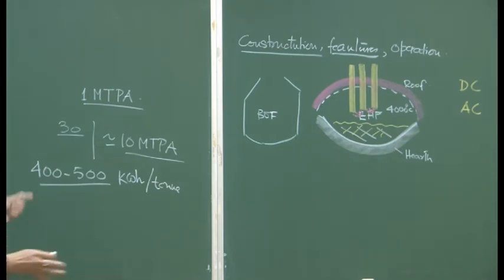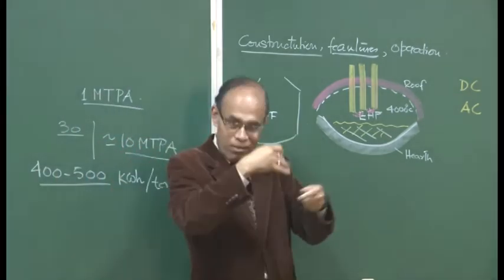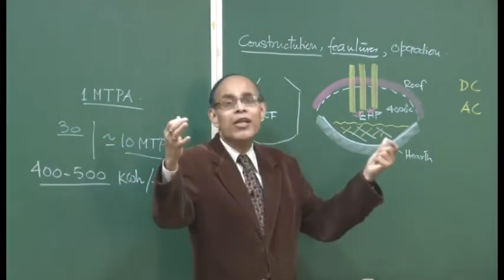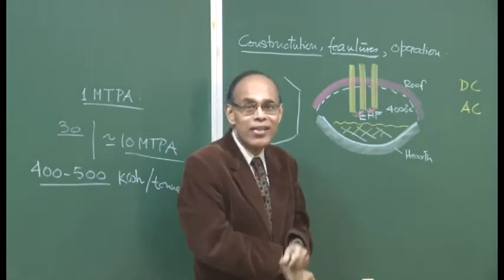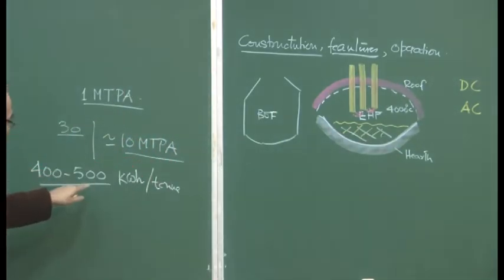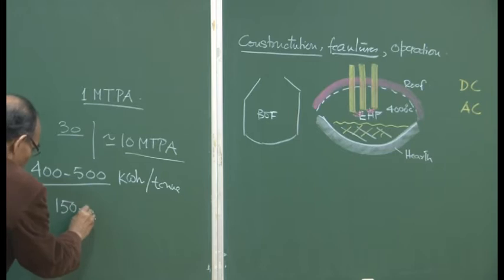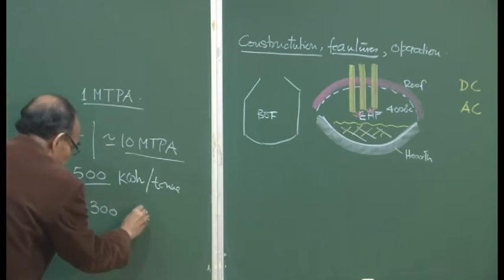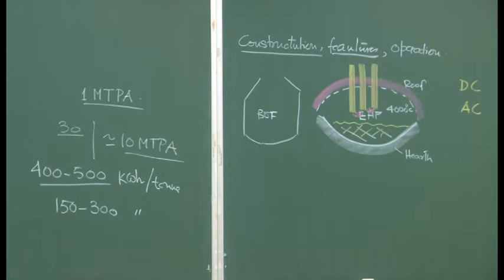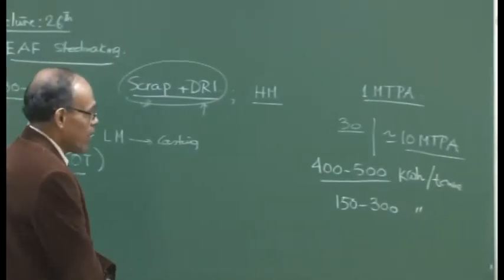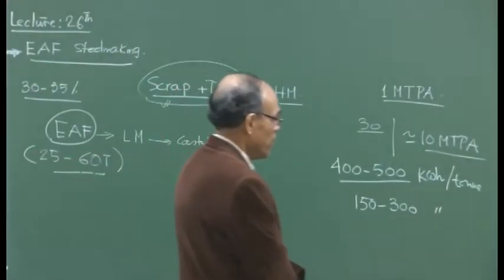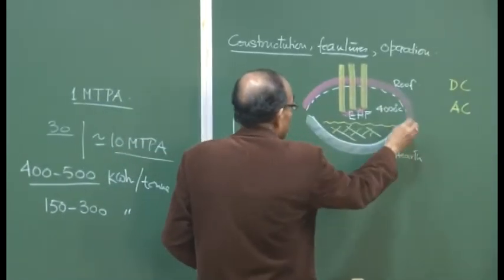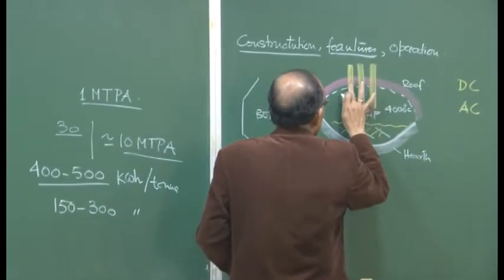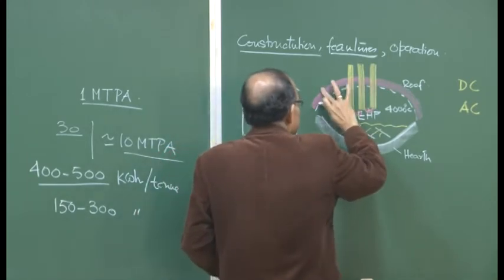And then of course, once it is melted, the refining can proceed, and all through this period of time there are going to be heat losses also from the furnace itself. So, on top of the bare minimum heat, this is the melting heat, you will require, depending on the furnace, somewhere around 150 to 300 kilowatt hour per ton of steel. That is the kind of power, and this is the refining requirement, this is the melting requirement of power in the system. So, you have, for example, off gas.